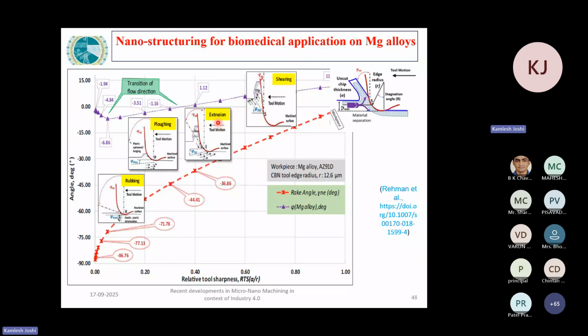The mechanism will convert from extrusion to ploughing, and machining will not take place, but bulging will take place on the material, and the angle of ploughing will keep on decreasing. Further reducing the relative tool sharpness to less than 0.2 by further reducing the uncut chip thickness, the mechanism will turn from extrusion to ploughing to rubbing only, and the tool will only rub on the material. It will not produce the desired machining effect.